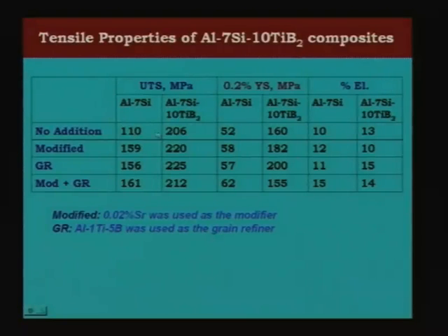So, one cannot achieve really very high strengthening here, but still you can see that if you take this aluminum 7 silicon alloy, without any TiB2 you get about 110 UTS, with TiB2 you get about 206. So, almost double the strength, and if you look at the elongation, 10% and 13%. So, you do not lose the elongation, that is very important to note.